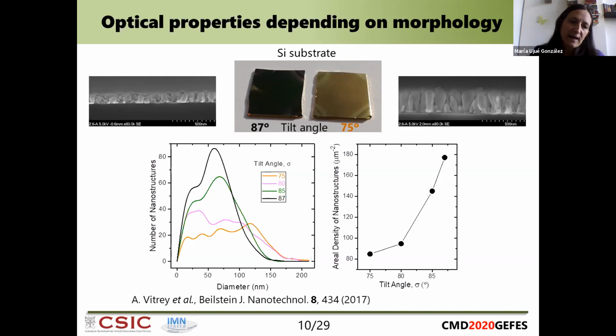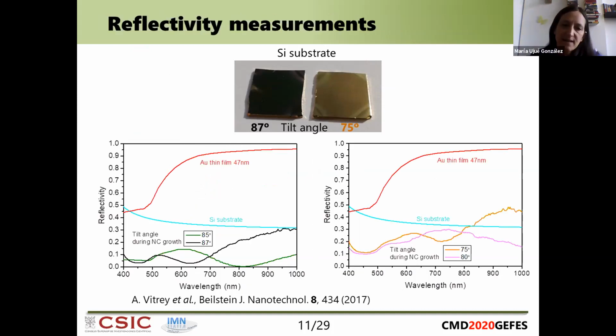And in the other case, we had a much narrower distribution in diameters, but on the other hand, they were much more inhomogeneous in terms of the height. So just as we could expect by just looking at the color of the samples, when we measure the reflectivity of the sample that was done at the high angle, we could see that the values of the reflectivity were very low in all the visible spectra. And in the case of the films deposited at lower angle, we see that still the reflectivity is low compared with a thin film, but the values were higher.